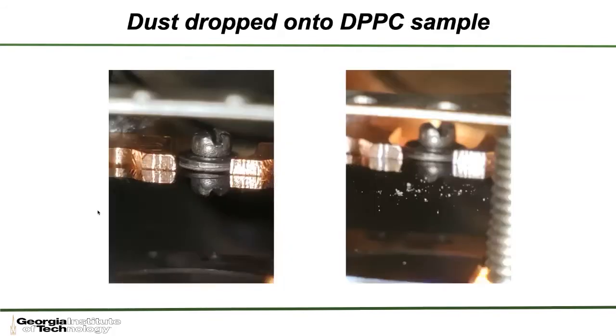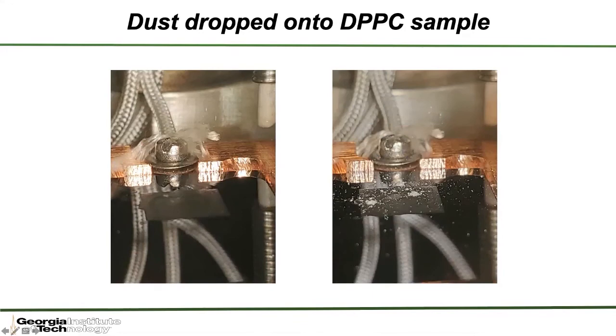So just real quickly, in the minute or so I have left here, what did we see when we dropped these dust grains onto the DPPC? So you can see here we've done a few experiments where this is the sample before, this is the sample after. I don't have a very good video camera, so it's kind of hard to see in live time. It takes a few minutes. But we're definitely getting these grains to drop onto our samples. Sometimes we get a lot of grains dropping onto our samples.